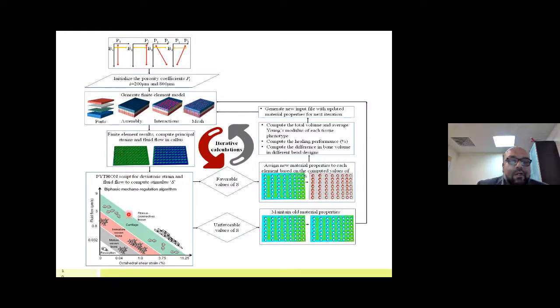And here, what we had is we have developed an algorithm that simulates the bone growth by looking at the strains on the tissue. So various micromotions lead to different strains, and these strains lead to different promotion of bone growth. So there was an algorithm developed, and we use this algorithm to study if a particular design of the pores or beads actually enhances tissue growth on the stem. This tissue growth is needed to enhance the stability between the implant and the bone.